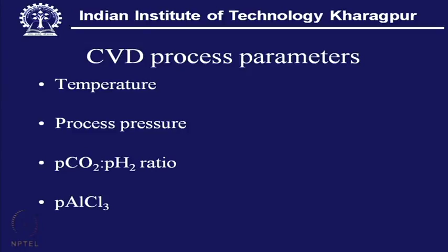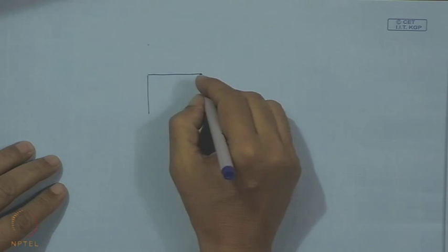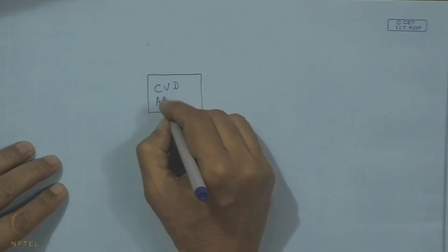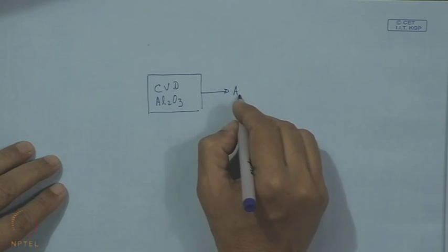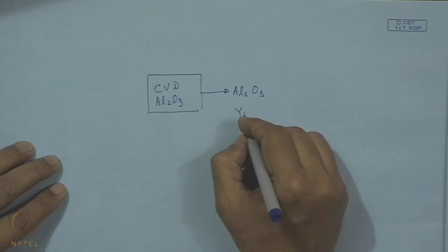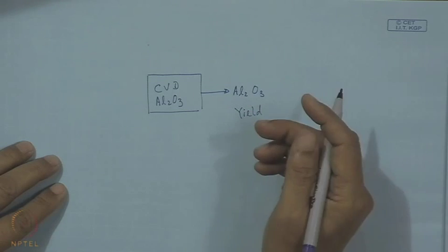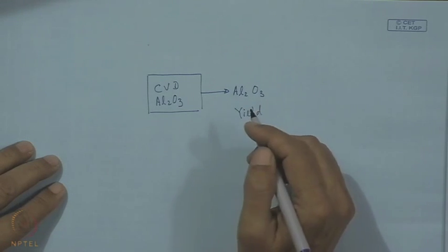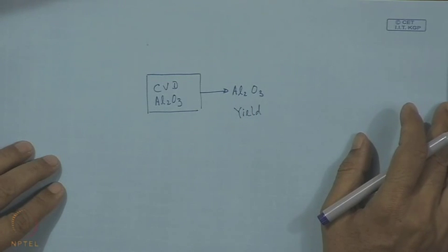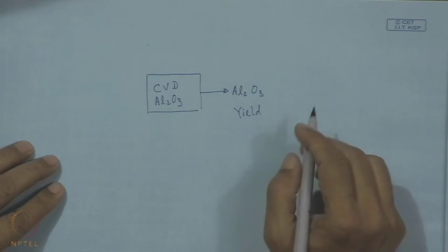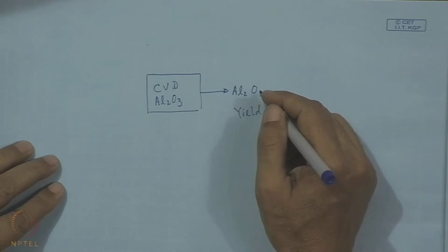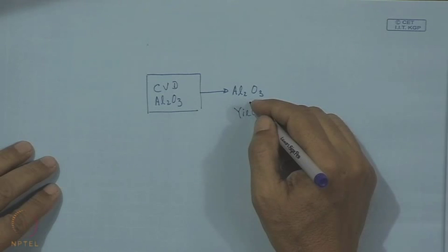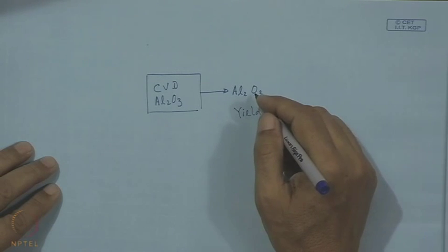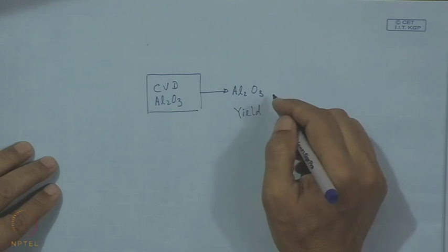Now, what are the process parameters for this CVD of aluminium oxide? When it is the CVD of Al2O3, on this side we want Al2O3, that means the yield of Al2O3, the growth in milligram per hour or micron per hour. That is one of the criteria, an index of production rate, and this is the outcome along with the morphology of the coating, that means whether it is a coarse coating or a fine grain structure with a smooth surface or rough texture, then the density of the coating. These are the issues to be addressed with this Al2O3 coating.